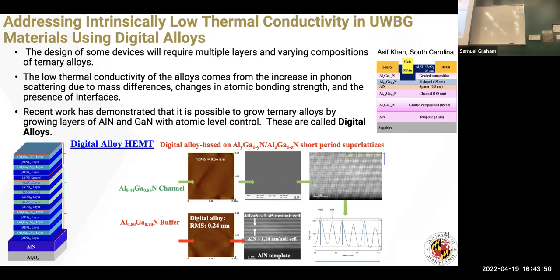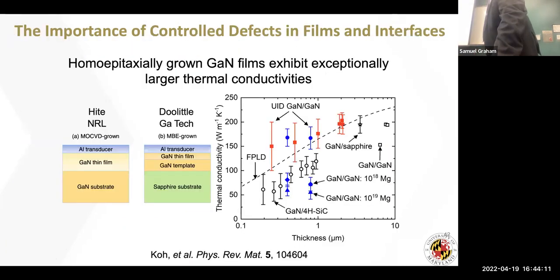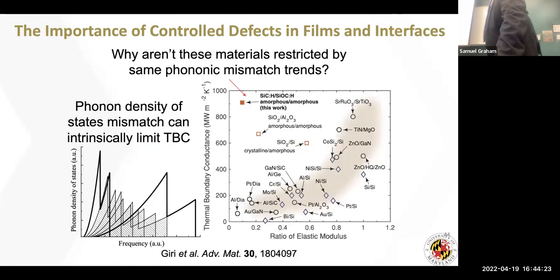And again, our colleague, Asif Khan at the University of South Carolina, can actually grow these in layers in microns of thickness. But most people that have studied these superlattice structures before have noticed that whenever you have more interfaces, you typically have something that is more thermally resistant. But I want to show you what we're finding in our research here. Because of the time, I'm going to skip through some of this, and I'd be happy to come back to this if you have questions.